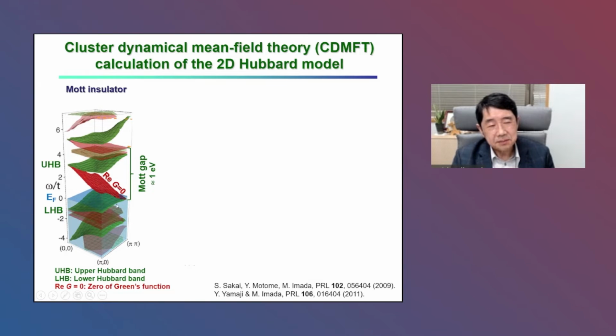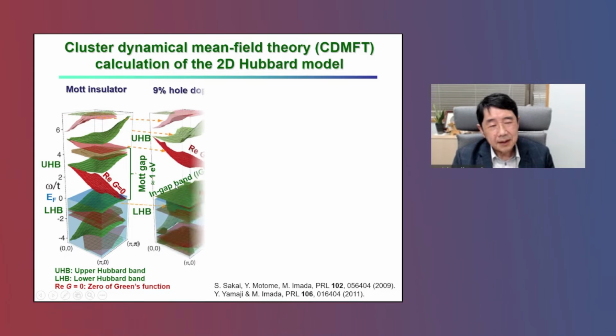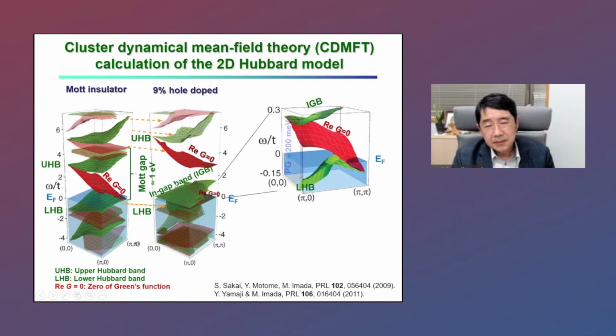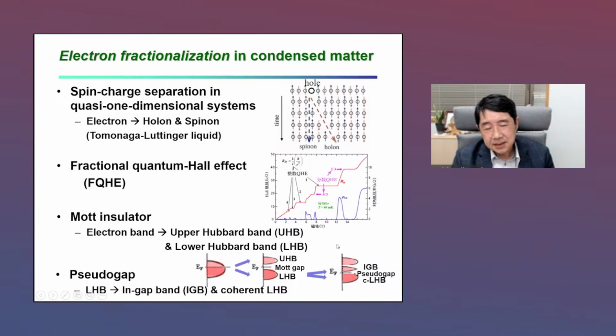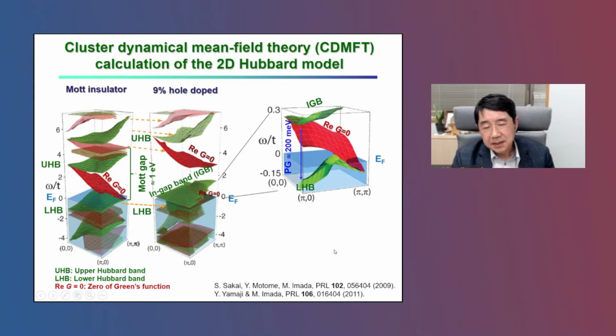Actually, this is a numerical calculation of the two-dimensional Hubbard model, showing the lower Hubbard band split by hole doping. This one is split into the lower Hubbard band and the in-gap band, like I indicated here. And this lower Hubbard band crosses the Fermi level and creates a so-called Fermi arc, as experimentally observed.